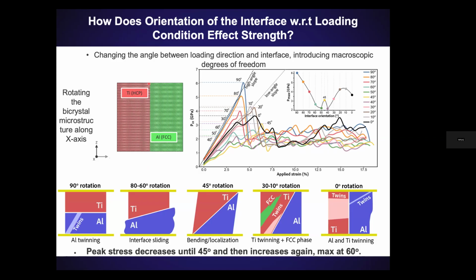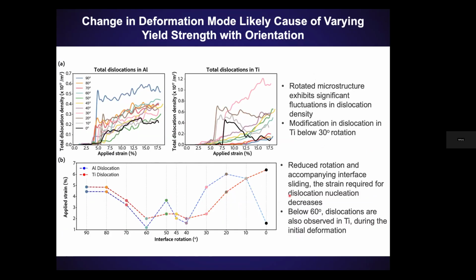What I can tell you from the stress strain response, if you just look at Pmax versus interface orientation, is that the peak stress decreases. You get a lot more deformation as you go from 90 degrees to 45 degrees because you're changing the critical resolved shear stress and nucleating more defects, for example, in materials with the loading. Then eventually, as you keep going up, you activate things like twinning in titanium and maybe even some phase transitions, which, by the way, I wasn't sure is real in titanium. But in molecular dynamics we're at pretty high stresses, and that could also be because of the potential that we're using. Basically, you can go from dislocation slip to twin nucleation as you change that loading orientation, and that seemed to have a much bigger effect on the mechanical response of the interface.